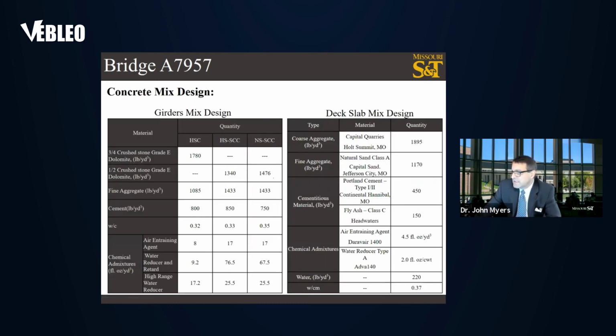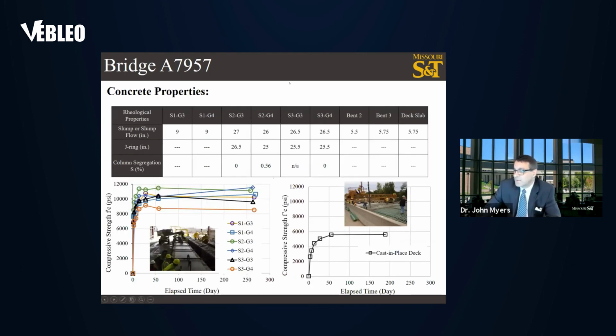I won't go into the details due to time, but the big thing to note in the SCC mix designs is that there is a reduction in the amount of coarse aggregate and an increase in the fines, as well as a reduction in the size of the coarse aggregate, as we have discussed about self-consolidating concrete. The concrete properties you can see here, both in terms of the compressive strength development, well above 8,000, as well as the property of the deck and some of the properties of the fresh concrete.